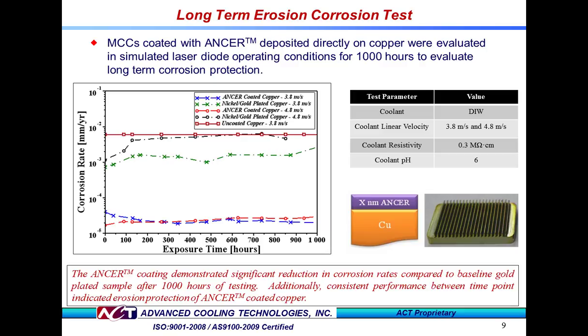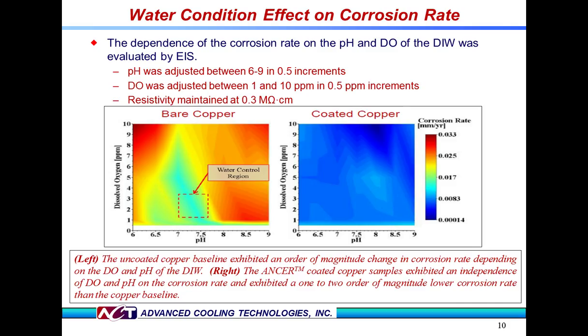The many colors on the bare copper plot on the left indicate an order of magnitude variation in corrosion rate from approximately 0.0083 to 0.033 millimeters per year. Recommended water control regions have a dissolved oxygen of approximately 1 to 3 parts per million and a pH of approximately 7 to 7.5, which occupies only a small portion of the plot.